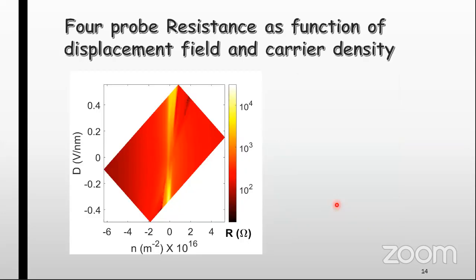First we measure a 4-probe resistance as a function of top gate and back gate voltage. Then by using this formula, we converted the XY axis into carrier density and displacement field. In this plot we can see that for n equal to 0, there is a sharp bright color, which corresponds to higher resistance in this color map. This is happening because of the change in band gap as a function of displacement field, and this is one of the characteristic features of bilayer graphene. Other than that, we also observed an asymmetric feature about n equal to 0.